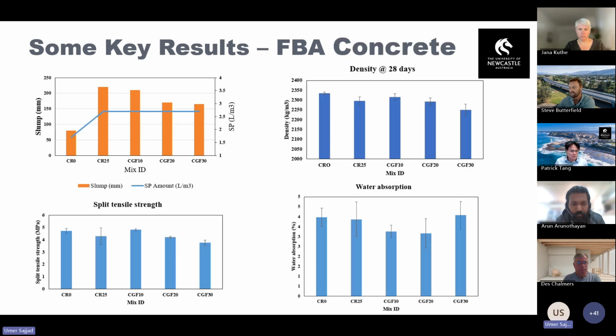These are some key findings from our research, which we have done here at University of Newcastle. So we have slump values. Here I am showing 5 mixes from the other major mixes we have done here in University of Newcastle. The first one is CR0, which means the control concrete without FBA and without any other addition or replacement. And CR25 is control concrete, but we have replaced 25% of natural sand with furnace bottom ash. And then the other 3 mixes are CGF10, CGF20, and CGF30, which is co-grinding of furnace bottom ash with slag. So we have replaced 10%, 20% or 30% of cement with ground FBA. If you have any question about the mix ID, let me know.